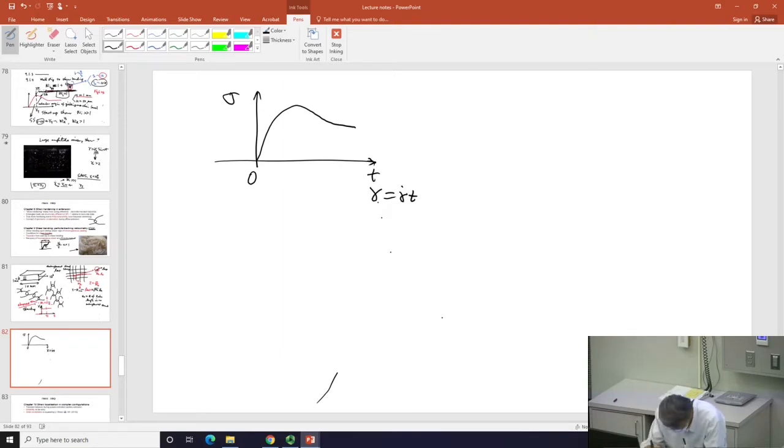Here I need to be careful when I say shear rate. I should be careful in the previous slides. As an experimentalist, what I can control is only V over H. Am I right? Gamma dot is always the shear rate inside the sample, which I don't necessarily know. You only know it if you assume, one, no wall slip, and two, the shear is homogeneous, there is no shear banding. Only in that limit can you say this. Otherwise you don't.